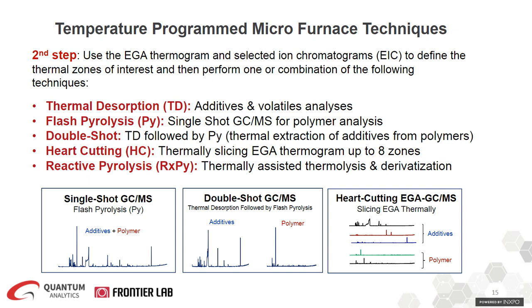As we talked, flash pyrolysis is a single-shot analysis, and you could see that on the left-hand side at the bottom. So in this technique, your pyrolyzer furnace will be programmed at a high temperature in a single temperature, for example, 600 C. So 1 GCMS chromatogram is obtained using the single-shot analysis where all the organic compounds are detected using the MS. So you get 1 GCMS chromatogram that is a combination of additives, volatiles, and all the polymeric components. So flash pyrolysis or single shot is the fundamental technique for polymer analysis.